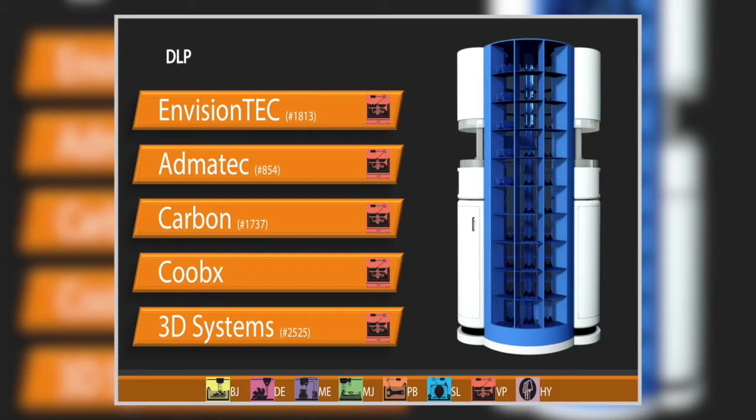Then there's a brand new one — about two months ago — the company pronounced Cubics. They operate in a similar fashion to Carbon and to Figure Four from 3D Systems, but in reverse. Instead of bottom-up, they're top-down, and instead of using oxygen to inhibit curing, they're starving the photopolymer of oxygen to accelerate curing, claiming up to 300 millimeters an hour. They're also automating right out of the box with something called Lift Cell — Lift Cell 2, Lift Cell 8, Lift Cell 12 — pairing machines with a central core that handles automatic part handling, storage racks for up to 60 parts, and resin filling.